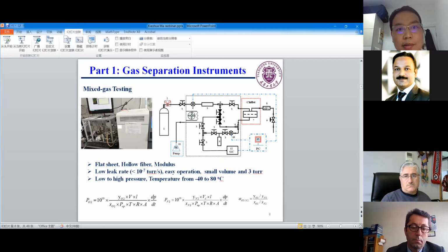And this is another, mixed gas testing instrument. This is its setup. For this, we can do the same thing for flat sheet, hollow fiber, and modules. And also we can do high temperature and low temperature, high pressure and low pressure testing. We use a pressure transducer to get the mixed gas permeability, and we use a GC to test the component ratio of those different gases.